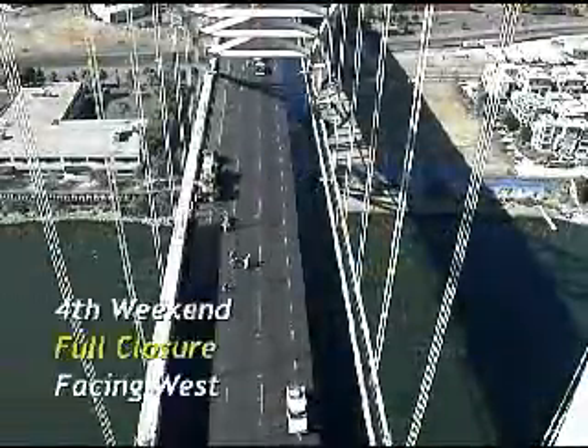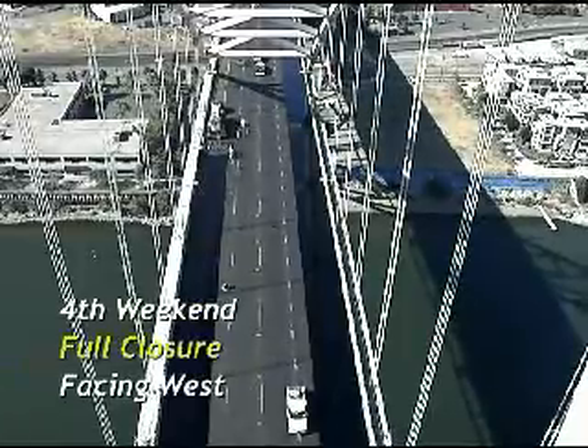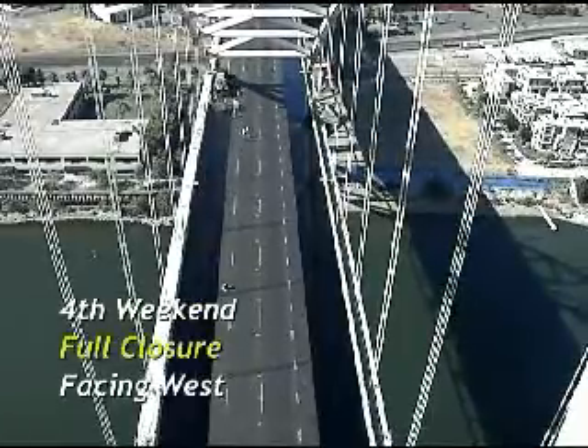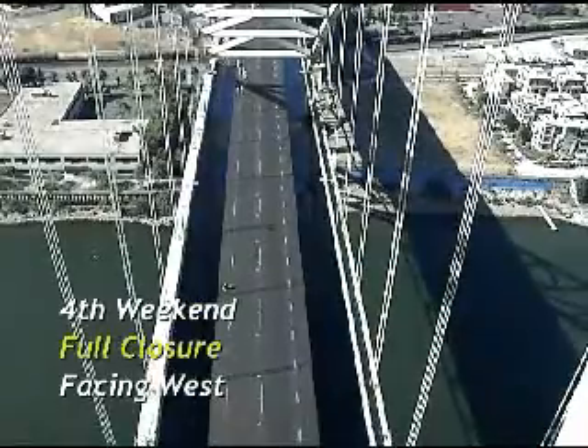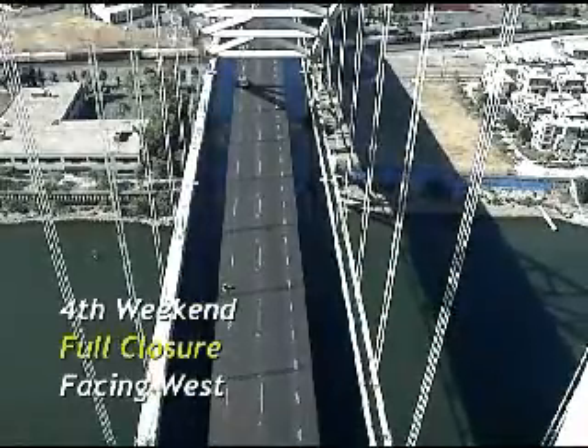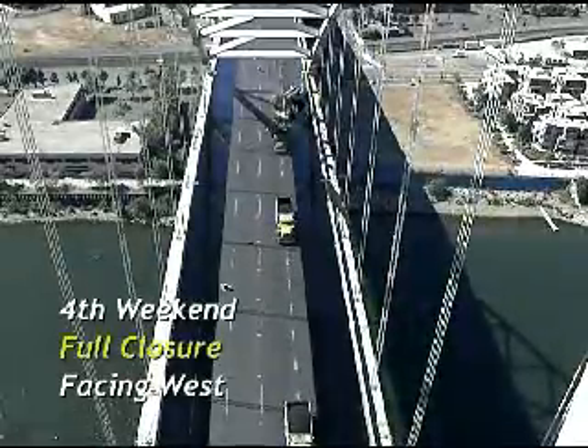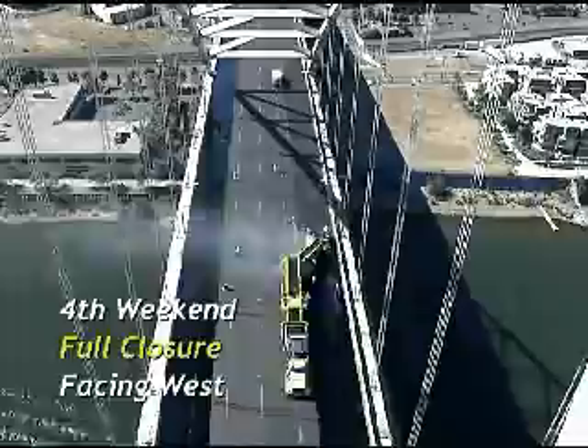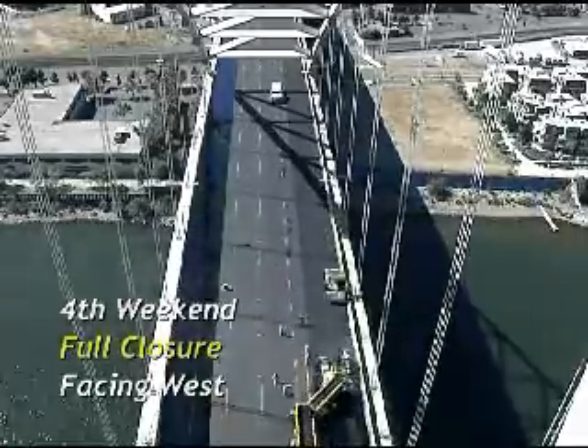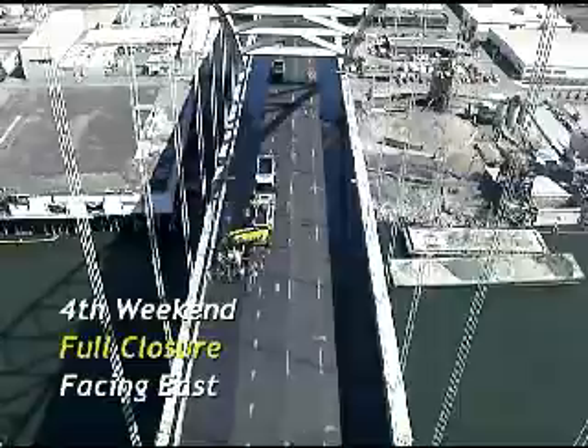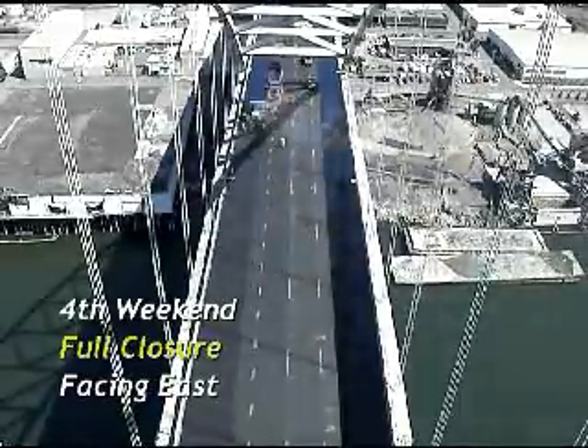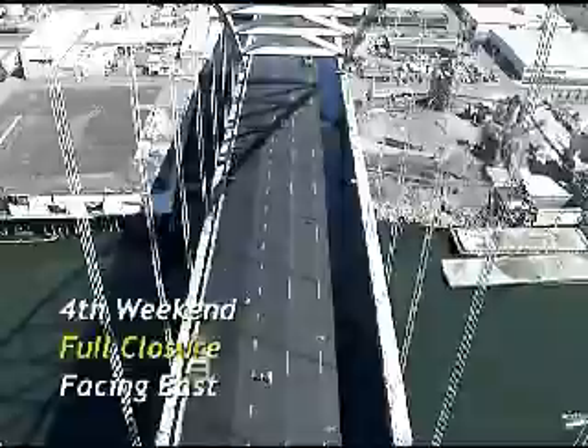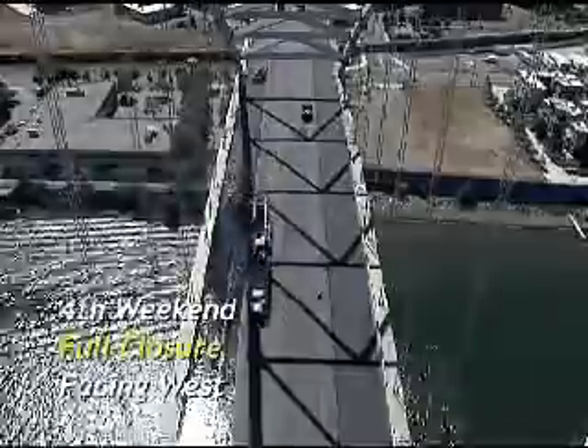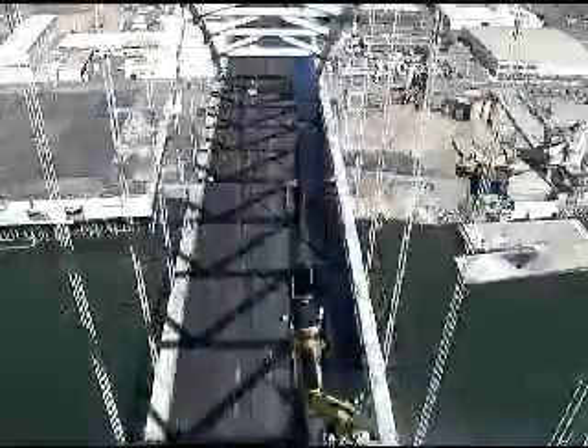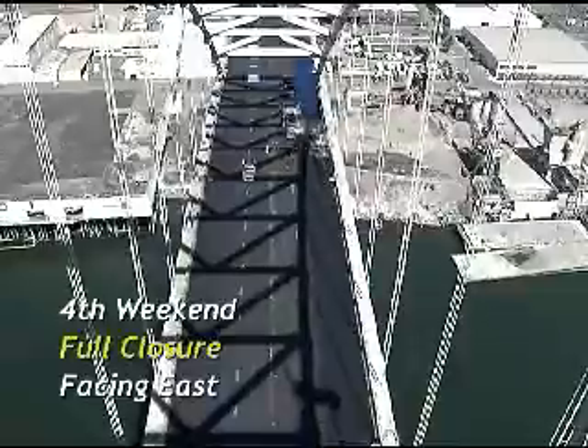Epoxy asphalt is different from regular asphalt in a respect that it's not produced as hot as regular asphalt. The epoxy asphalt is produced around 230 to 250 degrees Fahrenheit, whereas regular asphalt is produced over 300 degrees. The epoxy that's introduced into the asphalt needs heat and time to start the chemical reaction to make it start to set and harden. That's why we require the asphalt to sit in the back of the trucks for a set amount of time, so that lump of mass of asphalt, that hot asphalt, can initiate and start the chemical reaction of the epoxy. So the hotter the asphalt, the quicker the reaction will go.